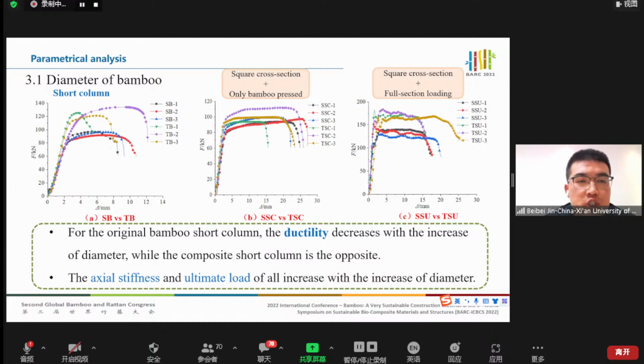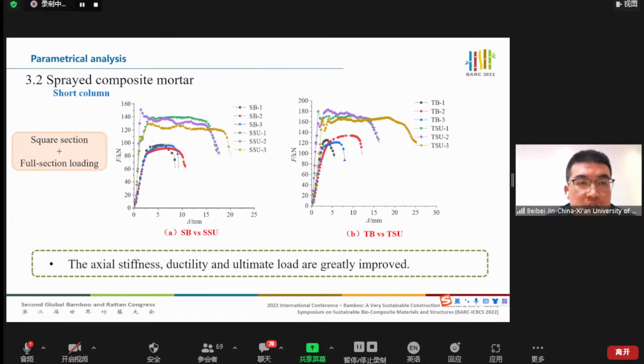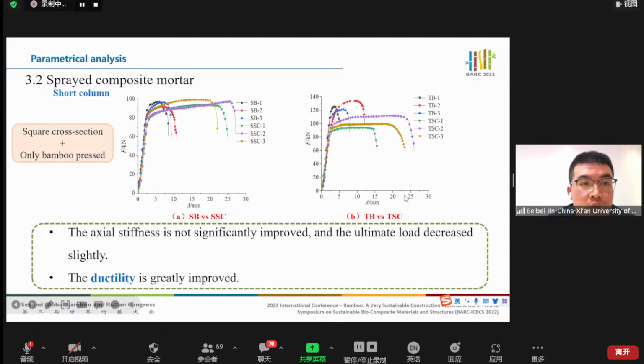And we also analyzed some data. First, the diameter of the bamboo. For a round bamboo short column, when the diameter increases, ductility will drop. But for the composite column, the axial stiffness and the ultimate load will go up as the diameter increases. Secondly, with the sprayed composite mortar, compared with the short column, square versus round cross-section, you can see that the axial stiffness is not significantly improved, and the ultimate load decreases slightly. The ductility is greatly improved.